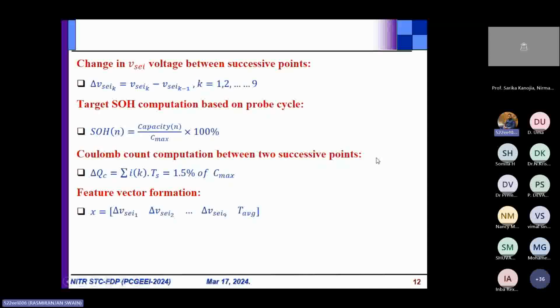Now I'll show you how the features have been computed, which are needed to train the neural network model. Here the v_sei voltage we have computed based on the circuit model, and the incremental change in the v_sei voltage has been computed here. The target SOH computation is based on the probe cycle current. Here the capacity comes from the probe cycle current, and that is the ratio with respect to the maximum capacity times 100%. That will give you the target state of health, which is treated here as the reference value.